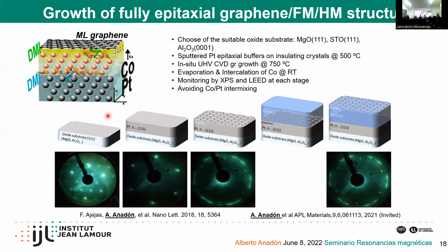So what we did, we were able to prepare in Madrid these complex structures completely in situ without breaking the vacuum. So we have a fully epitaxial stack, also using an oxide substrate. This is very interesting because it allows us to make devices. Normally, growing graphene by CVD requires a metal substrate, but we can overcome this problem by using a thin film of 10 to 100 nanometers, which we can grow epitaxially on an oxide substrate. This is done typically by sputtering at high temperature. We can use this buffer system to then grow a monolayer of graphene by CVD, as I said, without breaking the vacuum. So we have a clean system.